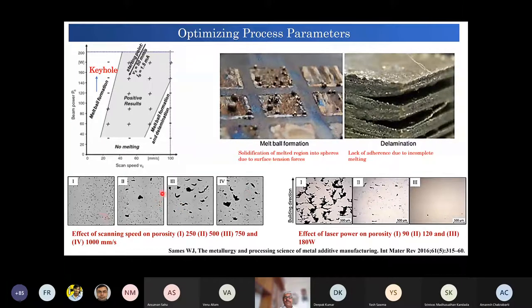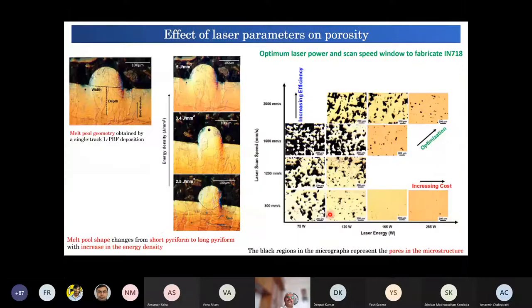For example, just quickly have a look: just by changing the scanning speed, the level of porosity has changed substantially from here to here. So just four times, from 250 to 1000 millimeter per second, the scanning speed has been changed. At a higher scanning speed, a lot of porosity has come in. Similarly, if one increases the laser power, at a higher laser power there is less porosity. At lower laser power, there is more porosity. So this is what it is.